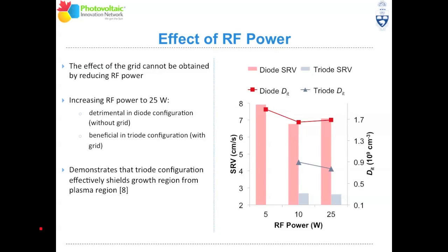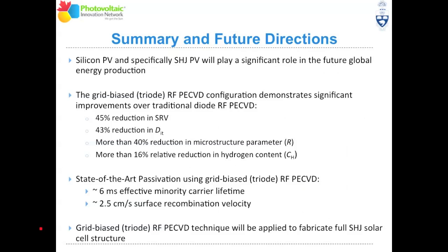For the triode configuration, which is shown in the blue, we found that when we increased the RF power, we actually got even better passivation. It went even below 2.5 centimeters per second. So we got really excellent passivation properties. So it demonstrates the fact that the triode configuration really provides unique properties and effectively provides another parameter in terms of controlling the energy and types of precursors involved in amorphous silicon film growth.